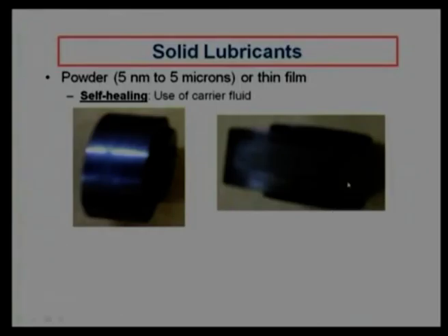When we operate this cam at maybe 60 rpm in lab experiments, after 3 hours of operation, we find that the complete molybdenum disulfide has been removed from the surface. You can see the worn out surface over here. This worn out surface clearly shows that there is no molybdenum disulfide. It has been removed from the surface. So, that is the major disadvantage. We apply molybdenum disulfide, and during operation it is removed.